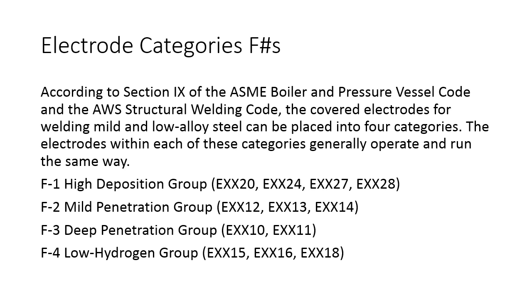Low hydrogen is F4. Even though it runs better in a flat position, it's a lot more difficult to get that stuff to go in an uphill or horizontal position and deposit really sound welds. So we've got those materials on the high end. If I qualify a weld procedure or qualify a welder with F4, the low hydrogen weld material, he can use F3, F2, F1, but it doesn't go the other way.